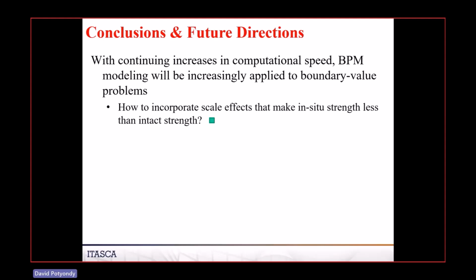Then we make all the particles half as big, and we measure the failure load, and we make it half as big again. And what we find is the failure load gets smaller as the particle size gets smaller. You can think of that as an example of a size effect that we see.